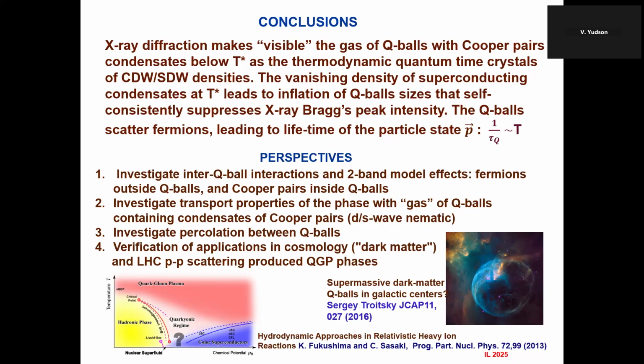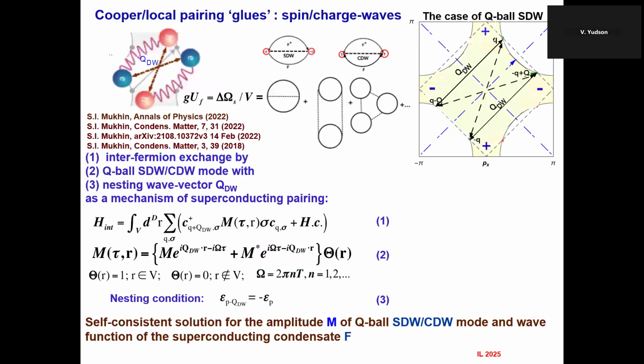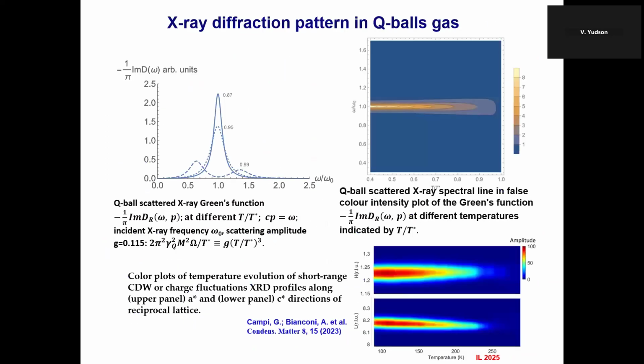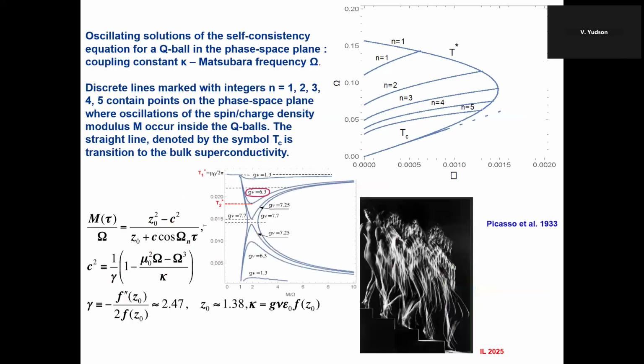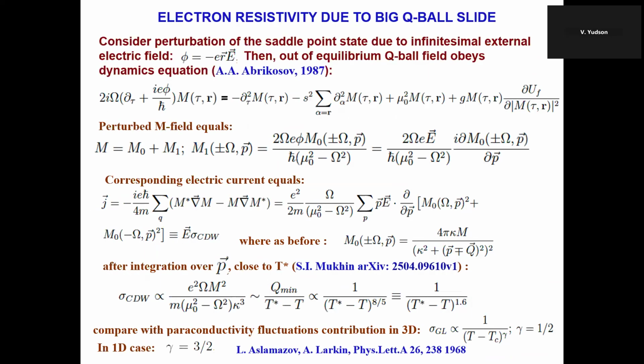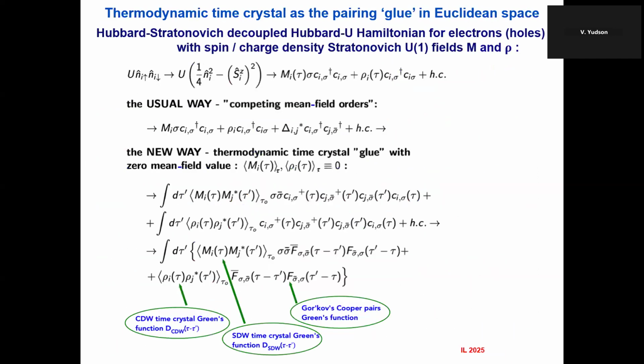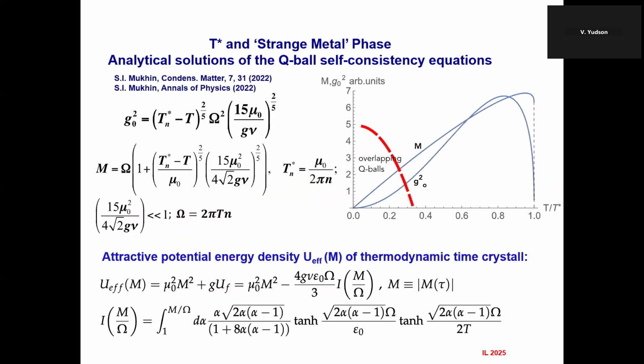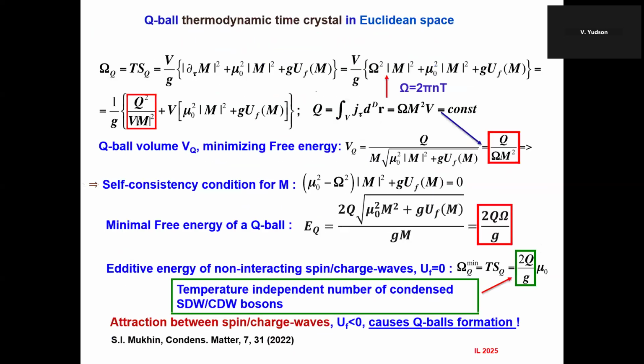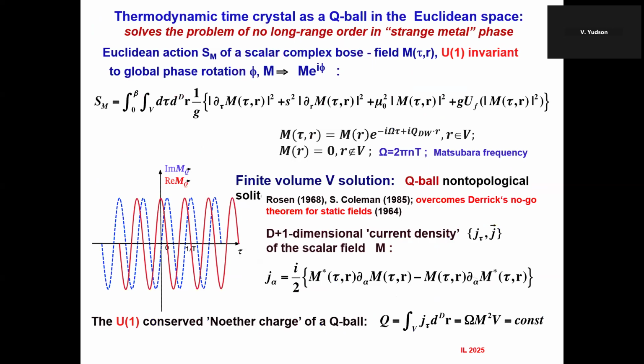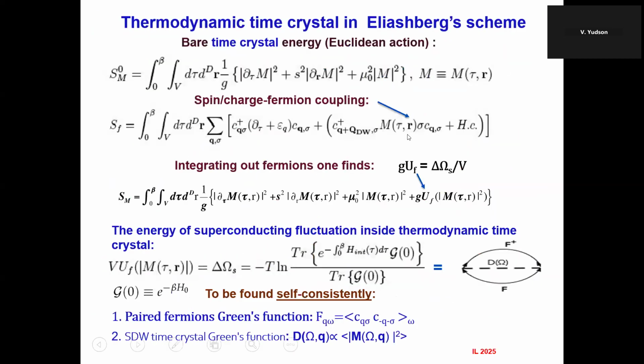And also what I wanted to notice, it is not shown here, but it proved to be the following: if you do this loop that gives you the contribution to the effective energy UF, you can do it from this interaction Hamiltonian for the spin wave and for the charge density wave. What is interesting, here, the interaction Hamiltonian. So if M is a spin density wave, it is the density of local spin interacting with the fermions. So then you have spin projection sigma.